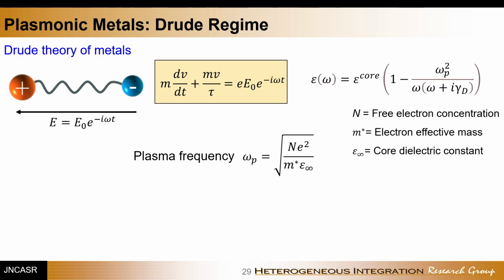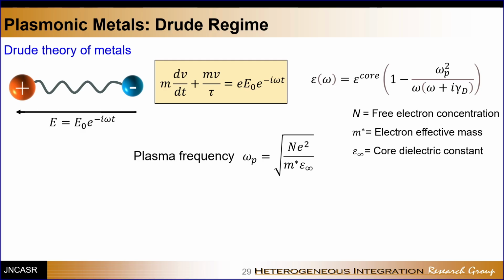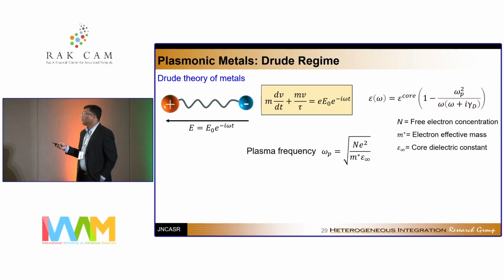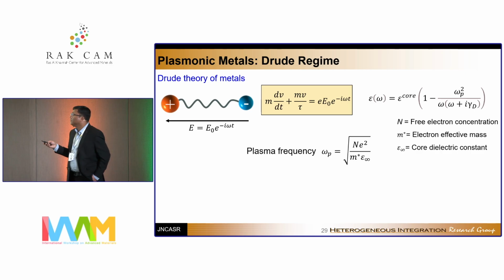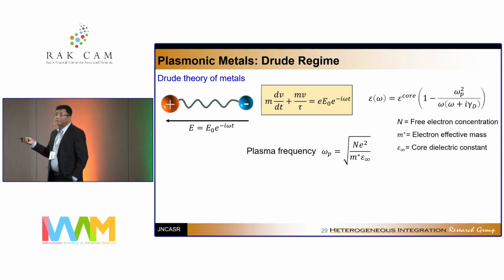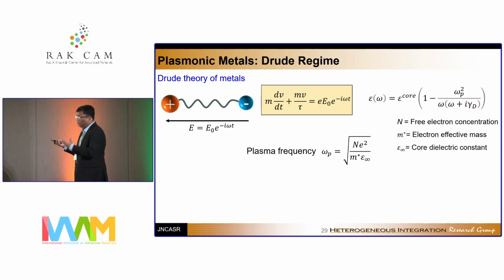So this is basically the Drude model. The Drude model gives you the optical response of most metals, right? And the Drude model is a semi-classical model where you basically look at the motion of an electron or any particle when you apply an electric field. From the Drude model, the plasma frequency omega p, which basically gives you the plasmonic response in a material, is given by carrier concentration times the electron charge squared, divided by m star times epsilon infinity, which is the effective mass and the core dielectric constant.